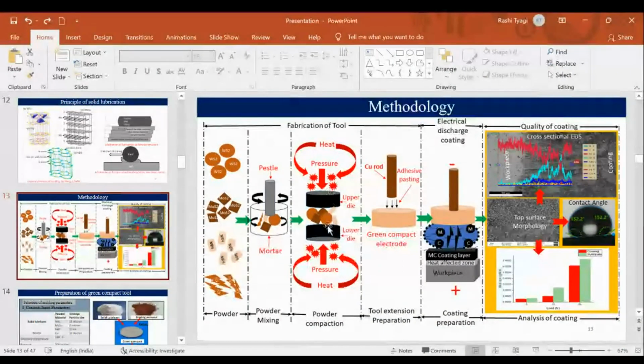onto the powders. We are using compaction pressure, and we are using heat. Heat means sintering temperature. We give some temperature to the machine. That temperature will help to make the green compact tool. So by applying low pressure and low heat, we can obtain the green compact tool.